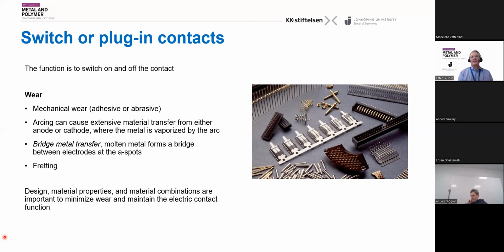If you plug out a device at home in your 240 volt system and the light is off, then you will actually be able to see sparks as well. And this arcing could also evaporate and transfer material between the contact bodies. You might also, in A spots, have the risk of micro melting, which is creating bridges between the materials, which is broken again. So that is also a type of wear. And then we have what is called fretting, which I will come to on the next slide. So the challenge is always, depending on the application, to find the right design, the right material properties, the right material combinations to minimize wear and to have a long lifetime that matches the product.